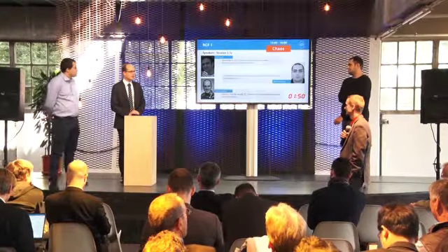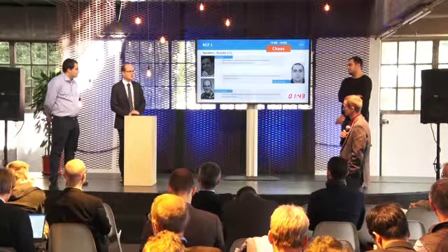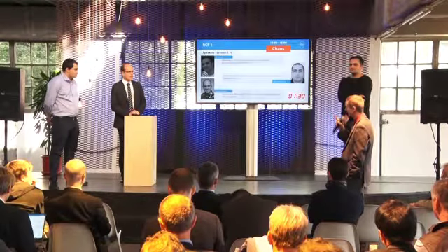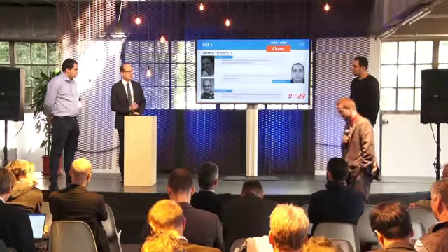The image you saw on the first slide was a magnetic particle inspection image from a test rig experiment. This experiment was run on the so-called old test rig. For the simulations, it doesn't matter. Of course, we want to use the capabilities of the newer test rig as well, which allows us to apply braking or acceleration moments to the wheel. This wasn't done in this test, so no, this was pure rolling. In this case, it was pure rolling, with an angle of attack in a simulation.